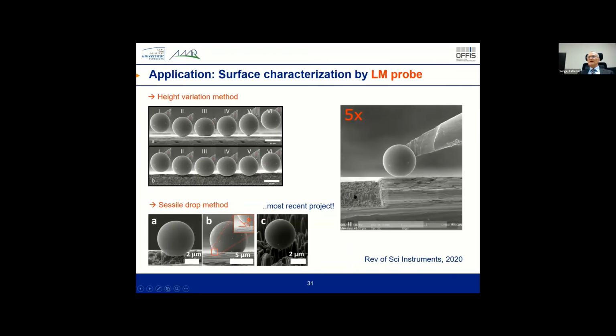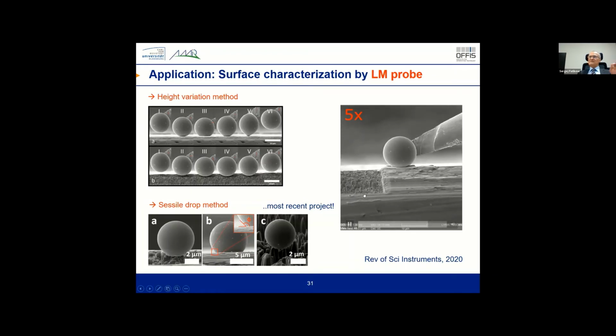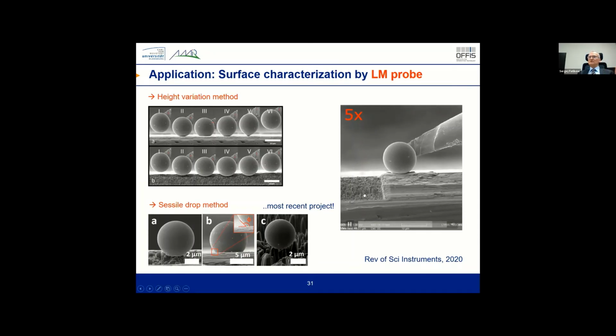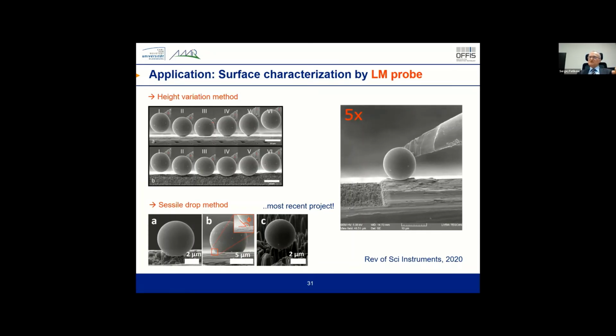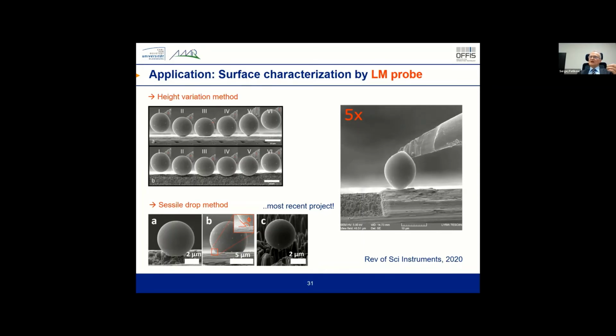So the more spikes you have in your surface, the smaller the van der Waals force. The adhesion force gets smaller and smaller if you have a lot of texture in your surface, and vice versa, of course. On the smooth surface, you have a lot of contact area, and consequently, the van der Waals force is pretty high, and the adhesion is pretty high. So you can do force mapping here at nanoscale, and this is extremely important, especially for bio-nano applications.